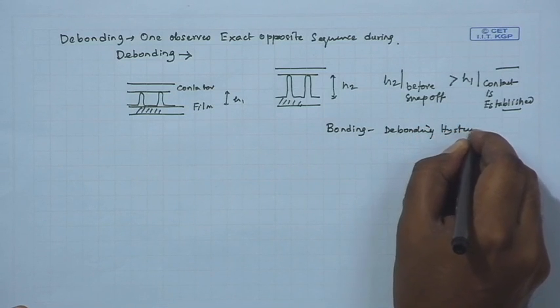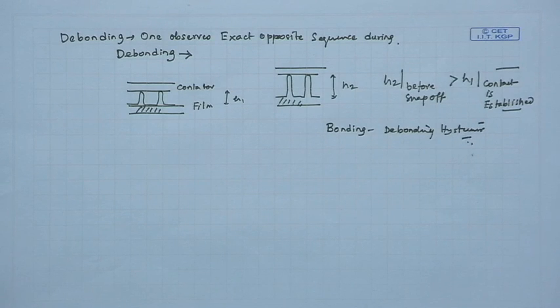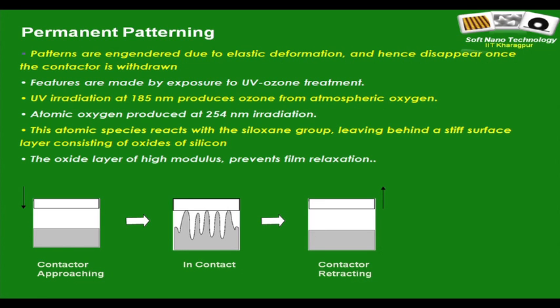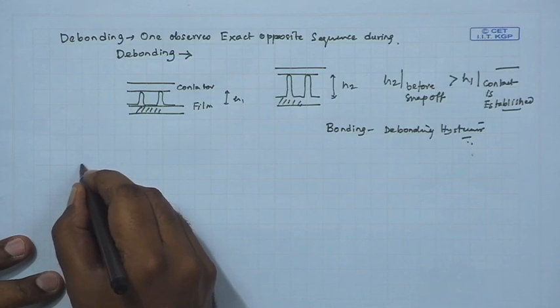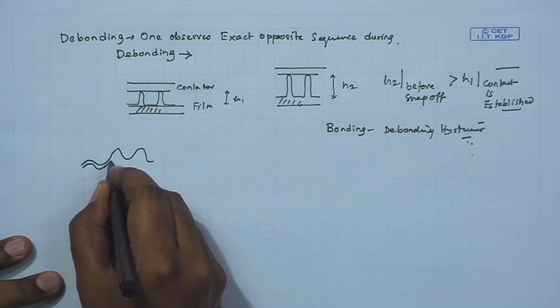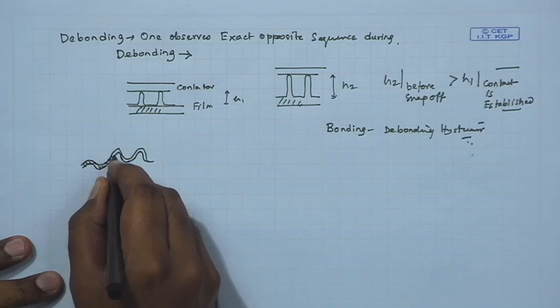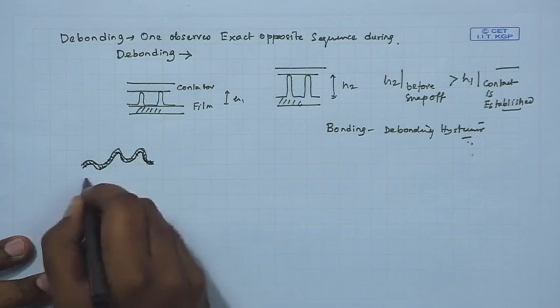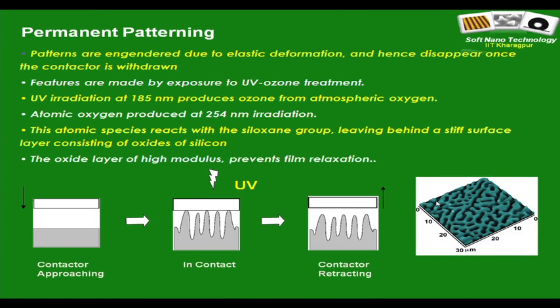Anyway, if one wants to use this technique as some sort of a patterning technique, the first necessary condition is to somehow freeze the structures. And there one can in fact take help of a bit of chemistry, because this is PDMS, polydimethyl siloxane, so it contains the Si-O backbone. It turns out that if UV light is shined on this particular film, a thin layer of oxides of silicon in fact forms over the film surface. And that is stiff enough that it prevents the relaxation of the film, and therefore you can make the patterns permanent. And as you can make the pattern permanent and remove the contactor, you can now do an AFM scan. Because in presence of the contactor, of course, you can't do an AFM scan. So one of the limiting factors in utilizing this technique as a viable patterning technique is eliminated, in that you can make the patterns permanent.